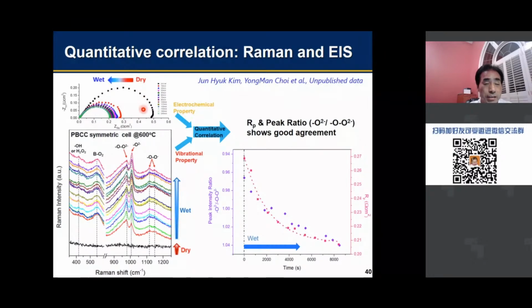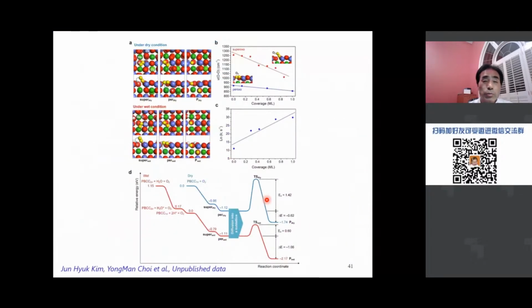So here the impedance decreases as you introduce water into the system. From dry to wet, the impedance shrinks, and we correlate this with the intensity of different peaks. That gives us an indication of the accumulation of different species on the surface and the interfaces. So we actually came up with a model to try to explain why, in the presence of water, PBCC actually has increased catalytic activity.